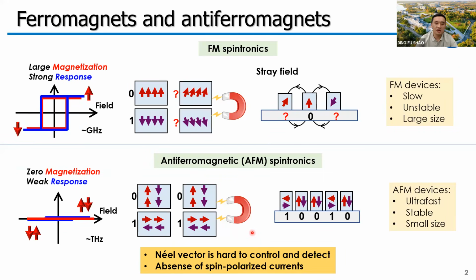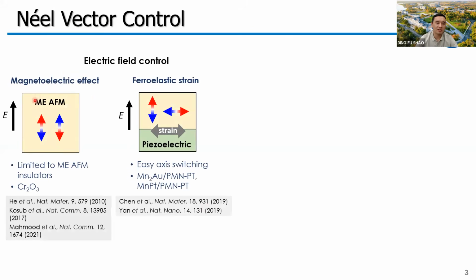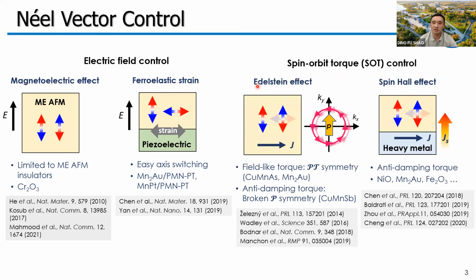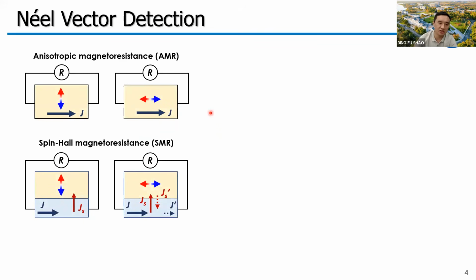In recent years, researchers have made extensive efforts to find efficient methods to control and detect the Néel vector. For example, we can find some antiferromagnets with a strong magnetoelectric coupling and use an electric field to switch the Néel vector. We can also deposit the antiferromagnets on top of some piezoelectric substrate and use strain to switch the easy axis of the antiferromagnets. A recent hot topic is using spin-orbit effects such as the Rashba-Edelstein effect or the spin Hall effect to generate spin-orbit torque on the antiferromagnets to realize the reorientation of the Néel vector. Although we have made very good progress to control the Néel vector, the Néel vector detection is still very challenging.